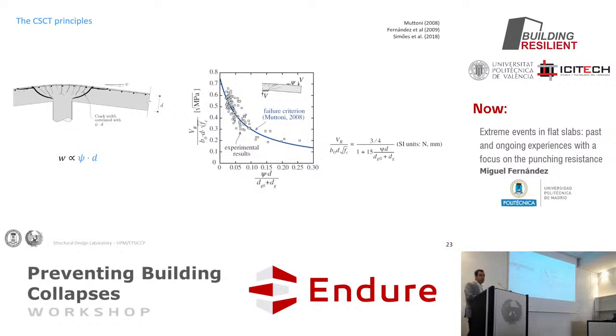This is, for instance, the hyperbolic failure criterion of the critical shear crack. And this is very, very simple. But please don't lose sight of the fact that the key parameter is actually the crack width, W. And I'm saying this going back to the presentation of Sarah.